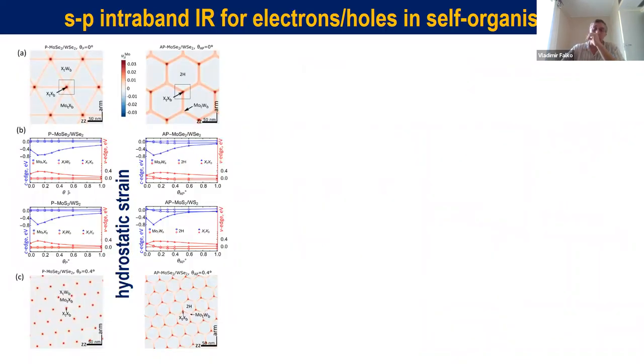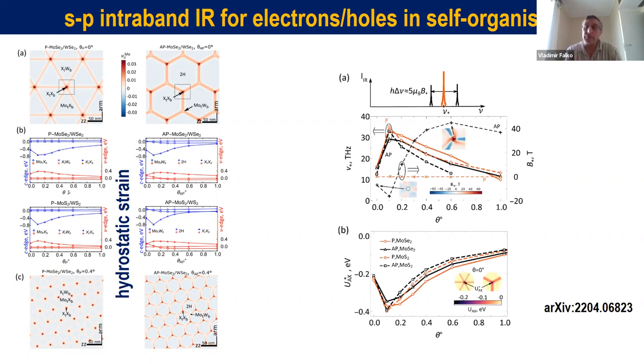So we basically modeled the strain for various misalignment angles in such structures, starting from 0 degrees to several, and looked at the evolution of the band edges. And from that, we were able to construct the distribution of band edge energy around these corners of the domain wall networks. We calculated the bound states for electrons and bound states for holes.